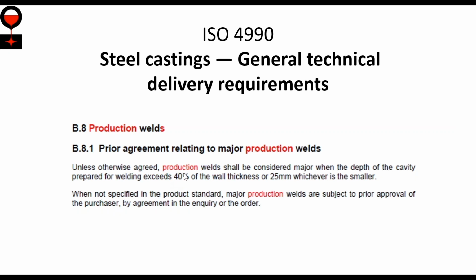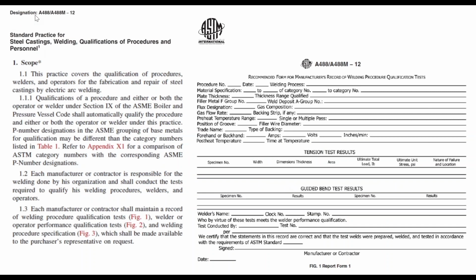One of the challenges we face is in the US, we normally use 20% of the wall thickness for a major weld. The Europeans use 40% of the wall thickness. That's not as big a deal as it might seem because both of us, if it's deeper than an inch, it's a major weld. So this is ASTM A488, and you can see that within the scope, it requires a record of the Weld Procedure Qualification Test, a PQR. The welder operator performance qualification test, and the weld procedure specification. All of these are required, and all of them are available to the purchaser.